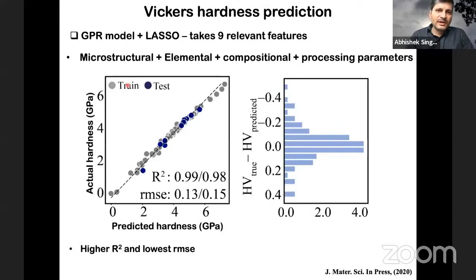Then we use microstructural, elemental, compositional, and processing parameters as our features, and apply the lasso to reduce them, which brings it down to just 9 relevant features. You develop a model, in this case for Vickers hardness, and you see how nicely it works. It gives you an RMSE within 0.13 to 0.15 and a very high R square of almost 99%.